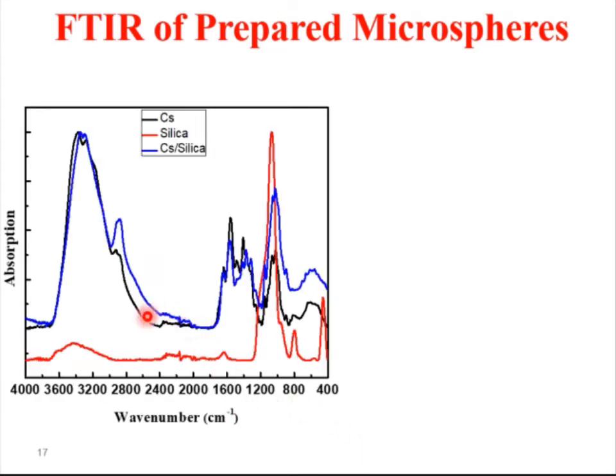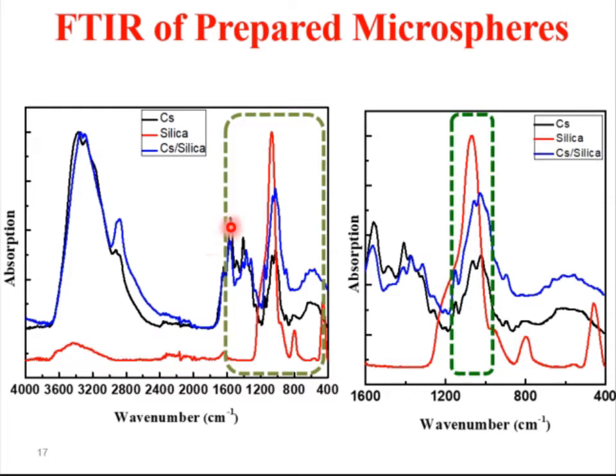Then FTIR was utilized for characterizing the prepared microspheres. This is for chitosan and silica and chitosan silica microspheres. We can notice that most peaks of chitosan were present in the chitosan silica spectra. However, there are some modifications and some changes in the spectra. Here, the presence of SiOC band and also the disappearance of SiOH band, indicating the presence of chemical interaction between chitosan and silica as well as physical interaction between them.